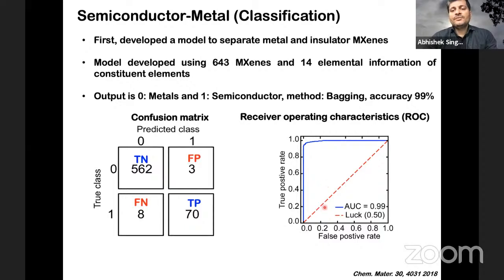Suppose I do this job by toss of a coin. Then I have a 50% chance of fail or pass, so that would be this 45-degree line. There is always a 50% chance of getting a metal or semiconductor. I'm not making any decision, right? It's just a random thing. However, when I start using features, mostly elemental features about my compounds, and create a classification model, this line shifts towards a rectangle, because the area under the curve gives you the accuracy of this model and can reach all the way up to 0.99, so almost 1. The more rectangular the shape is, the more accurate your model is. And this gives you a very highly accurate model to predict semiconductor or metallic MXenes.